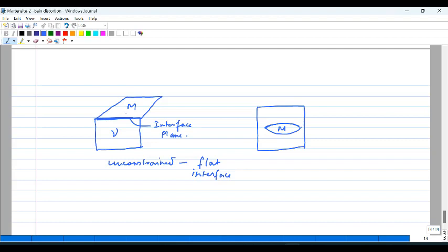It will remain same as the flat plane. So this is the constrained case where there will be strain generated in the surrounding matrix, and in order to minimize that strain, it will take up this kind of geometry as thin plates, and the habit plane will also have some curvature, but the overall plane remains the same as the previous case.